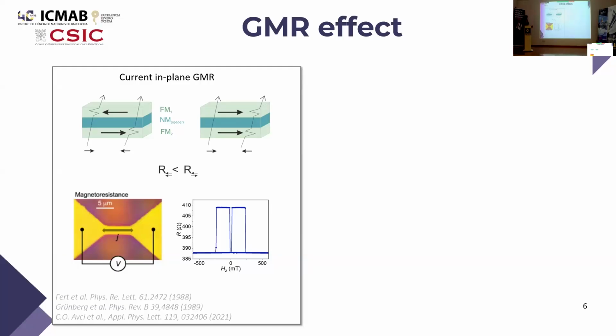So our first question was whether we can use another effect to read the state of a ferromagnetic insulator. For example, in metallic systems, we can use the giant magnetoresistance effect. This effect can be read in spin valve structures, where we have two magnetic layers separated by a non-magnetic spacer. The resistance of such a heterostructure depends on the relative orientation between these two magnetizations. And very importantly, we can read the signal in a current-in-plane geometry in simple two-terminal devices.